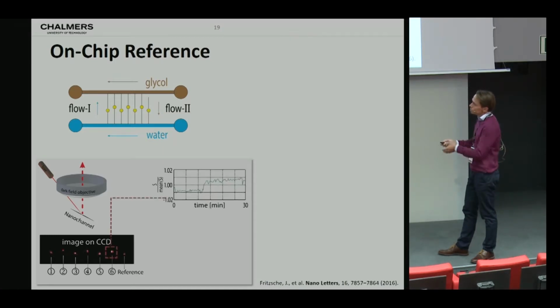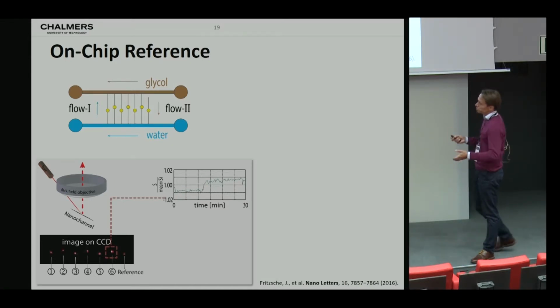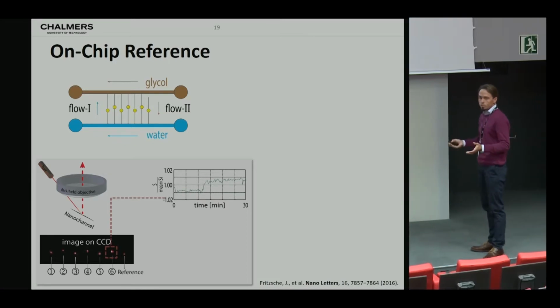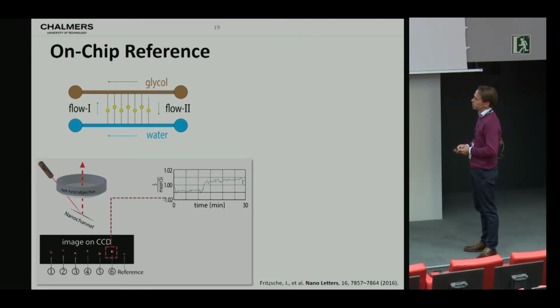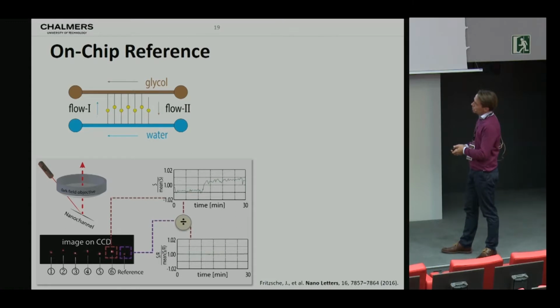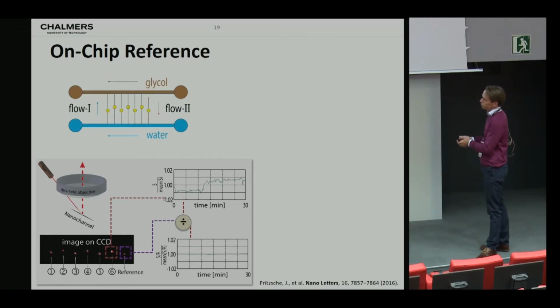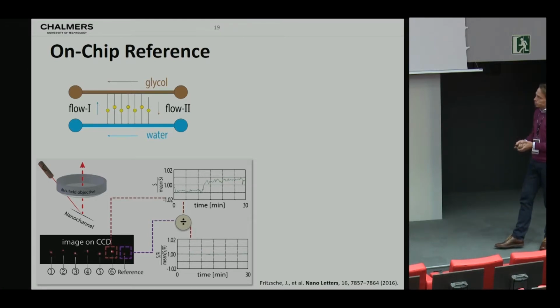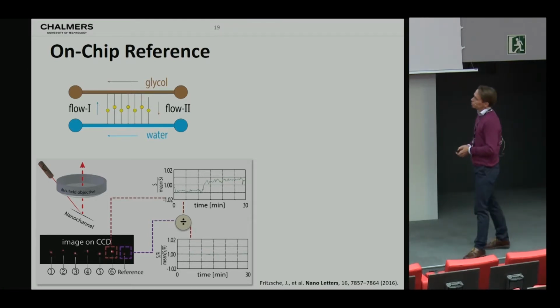Now, if we just measure the scattering intensity as a function of time from one of these particles, you will see that there is some fluctuations which mainly stem from the light source, which is not perfectly stable over time. But if we now divide the signal from this particle by the reference, we get this very flat baseline here for a time span of about 13 minutes. Now, why is this interesting? It's interesting for a number of reasons.